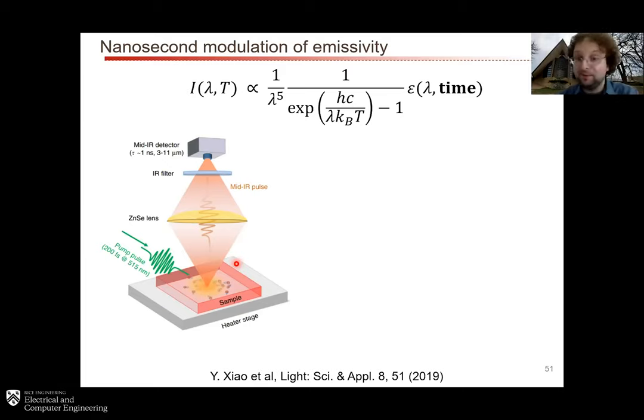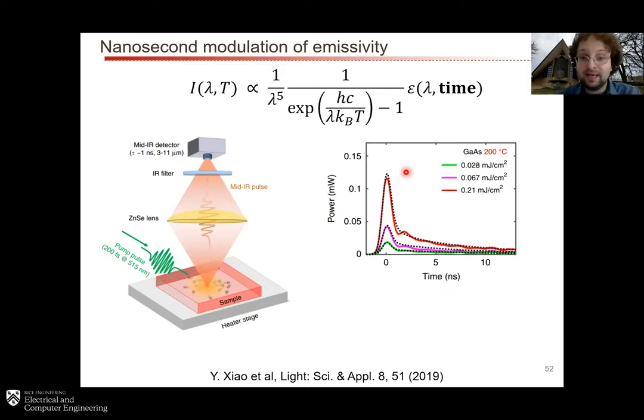So we took some samples, which in our case were just undoped wafers of silicon or gallium arsenide. We pumped this thing with high energy femtosecond pulses in the visible, in this case about 515 nanometers. And then we sent the output of the sample, which was sitting on a heater stage, into a mid-infrared detector with some filters in front of it. And what we were able to observe was that the power versus time could be modulated quite significantly. In this case, the pulse is just a femtosecond pulse, so on this axis it's just right here, and you can't see it at all.